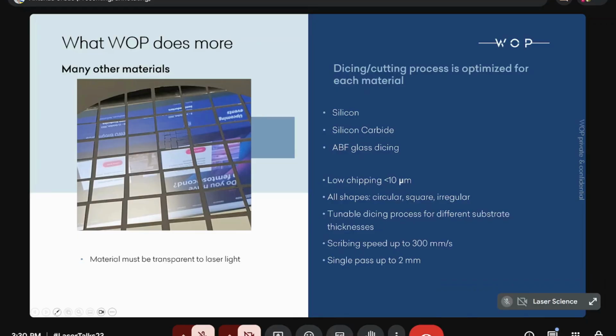They have to penetrate into the material to build this needle, meaning that the material must be transparent. So if we work in the transparency window for silicon carbide or ABF glass, we can achieve chipping better than 10 micron. Normally it is a couple of microns. We can do it in all shapes. And of course, we can tune the dicing process for different thicknesses.